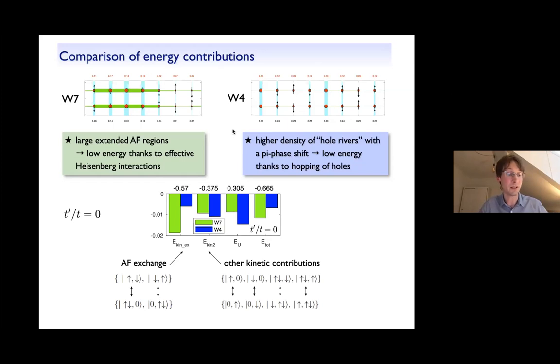So here first for t prime equals 0. Here I show you the different energy contributions in these bar diagrams, and the values have always been shifted by the number indicated on top. Here I show you a comparison between period 7 and period 4 stripes, the blue one, of the matrix elements which are relevant for the antiferromagnetic superexchange, so matrix elements between singly occupied sites and then a doubly occupied site with a hole. As we argued before, we clearly see that this is much lower in energy for the period 7 stripe, thanks to these large antiferromagnetic regions, compared to the period 4 stripe. Now this comes at the cost of a slightly higher energy of the U term, because the density of doubly occupied sites is larger in the period 7 stripe.